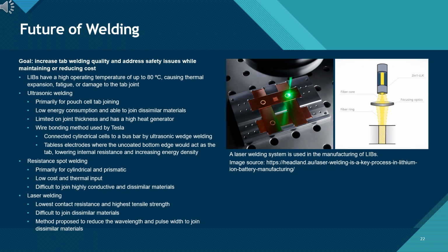Tesla's wedge-bonded, tabless approach is an evolution of this concept, reducing internal resistance and improving energy density. Resistance spot welding remains common for cylindrical and prismatic cells due to its low cost, but it struggles with highly conductive or dissimilar materials. Laser welding provides the highest joint quality, with excellent tensile strength and the lowest contact resistance. Its challenge is joining dissimilar materials, which has motivated research into shorter wavelengths and pulse widths. The image here illustrates a laser welding system used in cell manufacturing.